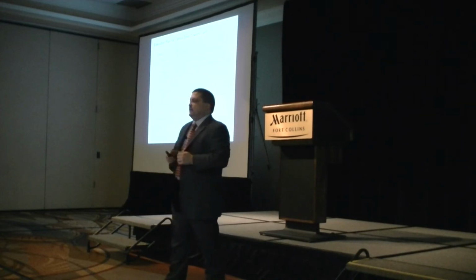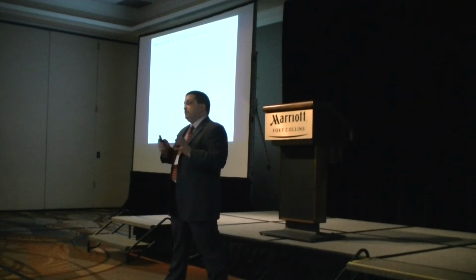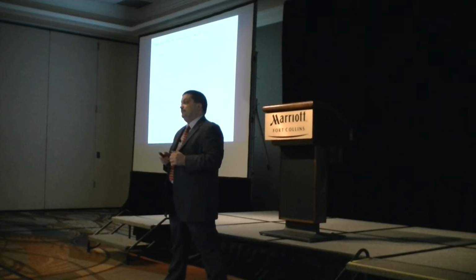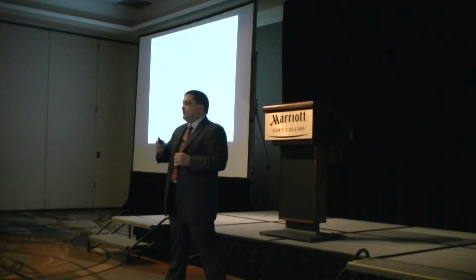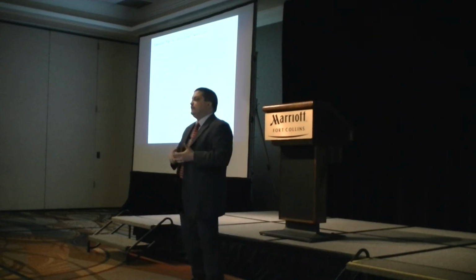Bundling inspection: we probably focused a good amount of time on bundling. At the beginning of the project, we had over 1,500 non-conformances in the yard based on bundling. After we put additional focus, additional inspectors on each shift, by the end of the project, we had that down to less than 80.